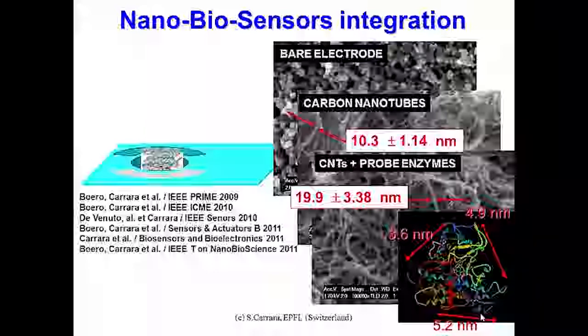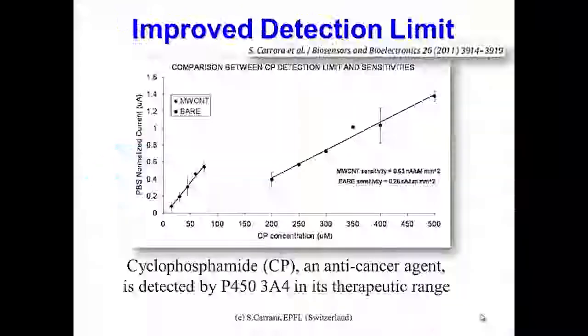You can recognize here the heme group of the protein, and it is roughly, not exactly a ball, a bit more a piece of cake. But what you can see is that the size is close to 4 or 5 nanometers, so that means that the increase in the apparent size of the carbon nanotube corresponds to a single layer of protein just surrounding every carbon nanotube fiber. So we can imagine having transferred onto our electrodes the carbon nanotubes and functionalized them with a coating of a single layer of the protein.